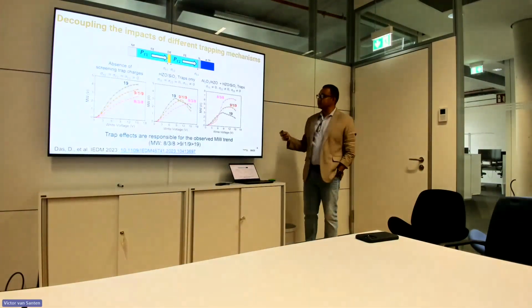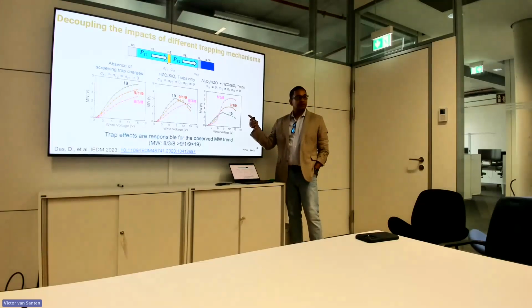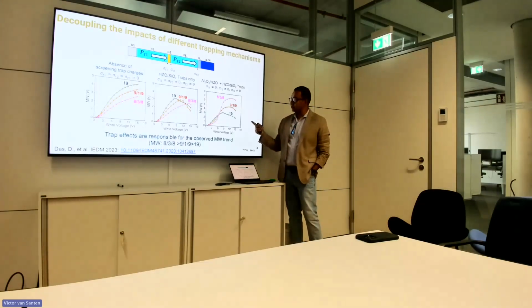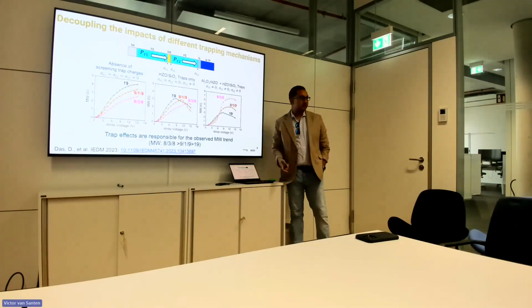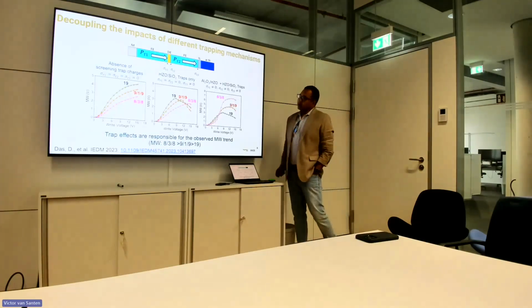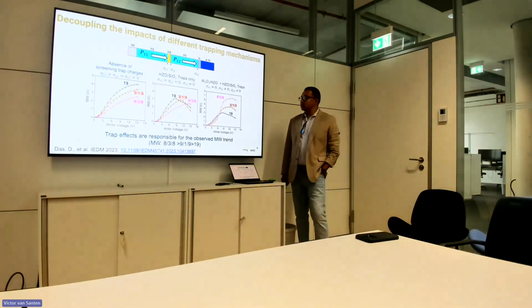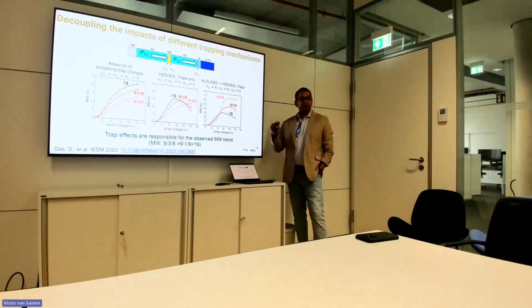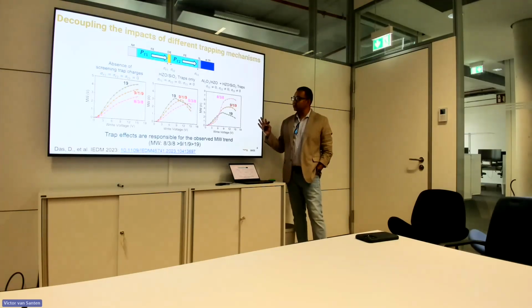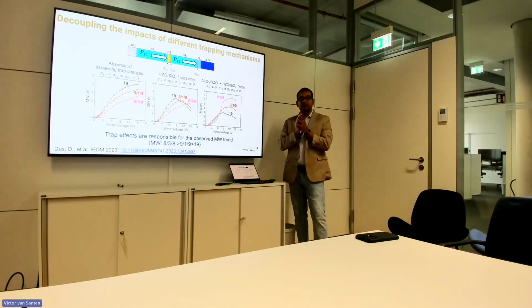And then we very clearly see that the experimental trend is captured here, meaning that when we put in the aluminum oxide, there is a massive enhancement of the memory window. So I'll not talk more about the simulation in this presentation, but if you want to learn more, we'll be very happy to share what the underlying assumptions were. Now, I think the underlying assumptions were reasonable. In all of these cases, we had about 15 parameters. Whenever we do a simulation with 15 or 20 parameters, you can fit anything.